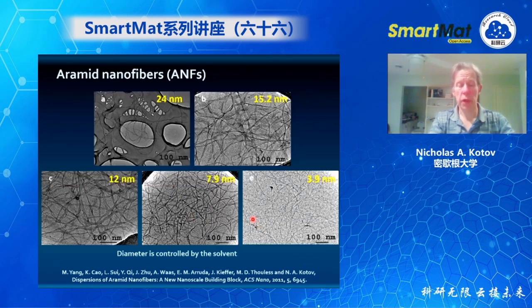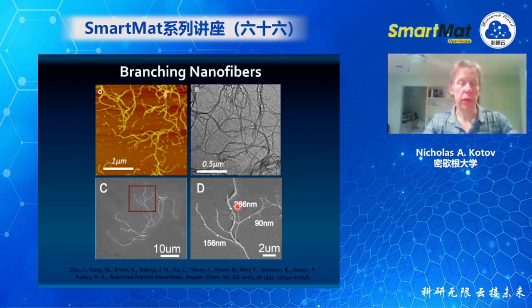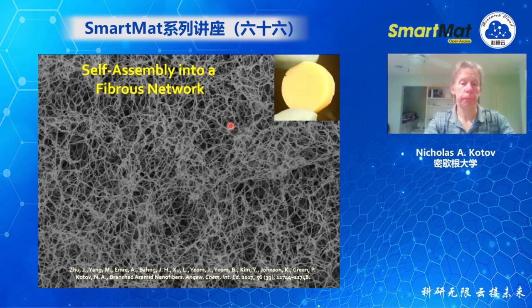And in this case, we form aramid nanofibers, and there are now many people who are working and doing fantastic work in this area. I was actually stunned how many interesting and unique materials, including 3D printing, are done now by using this and similar kind of aramid fibers. One of the unique properties of these fibers made in this way is that they're branched, so they are entangled very easily, and also they can be wrapped with soft polymers also quite easily. And as you can see, indeed, they form this entangled complex network structure, which resembles cartilage.